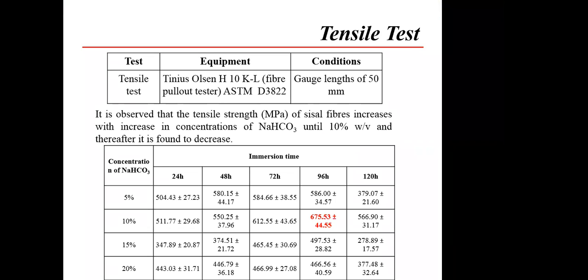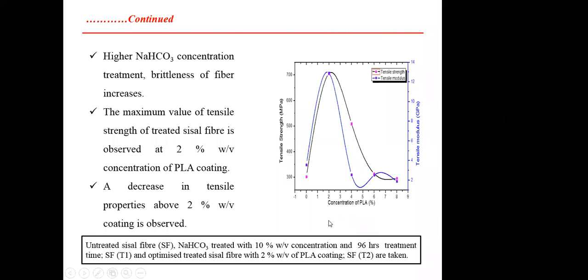Firstly, I have done the tensile test on a Tinius Olsen machine at MIT Allahabad. We can say from the table, the optimum value is obtained at 10% NaHCO3, sodium bicarbonate, and the optimum immersion time is 96 hours. This concentration and immersion time provide the optimum results of tensile strength.